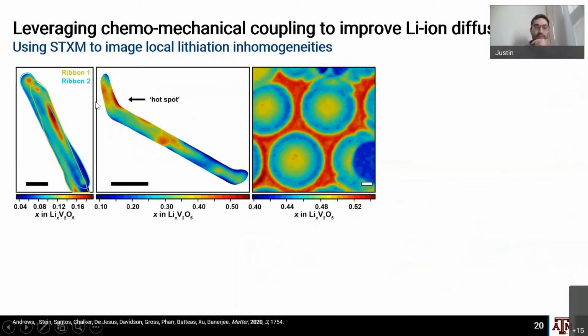And so if we dig a little bit deeper and we actually do principal component analysis and generate some composition maps, what we see is that around the curvature where this nanowire is strained, on the compressive side of the nanowire, we get generation of a hotspot. So something about the way that nanowire is strained there, it lithiates much more quickly on the compressive side of that, and then also is slightly delithiated near the other bend in that nanowire.